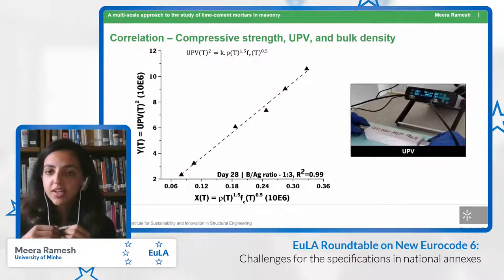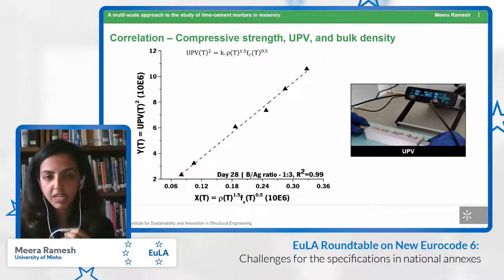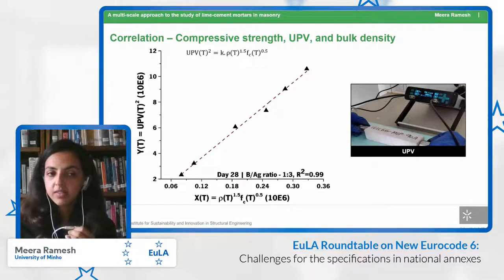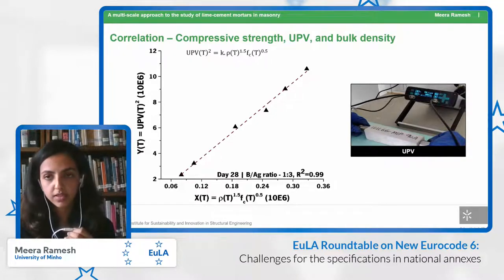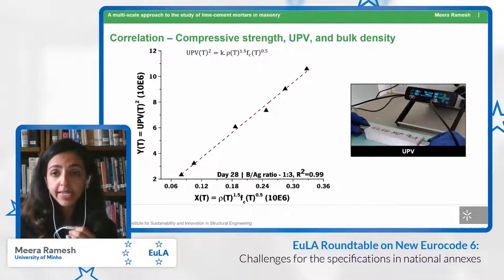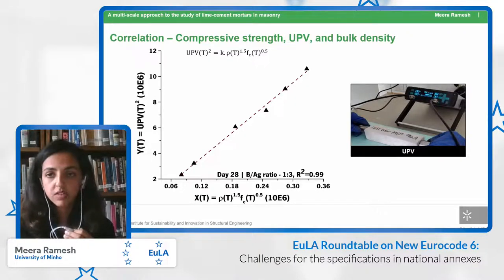We also found another way to try and estimate the strength of a mix, which is by using ultrasound velocity. On the y-axis, you have a function of ultrasound velocity, and on the x-axis, you have a function of density and compressive strength. And we found this to be linear for almost all cases that we studied.